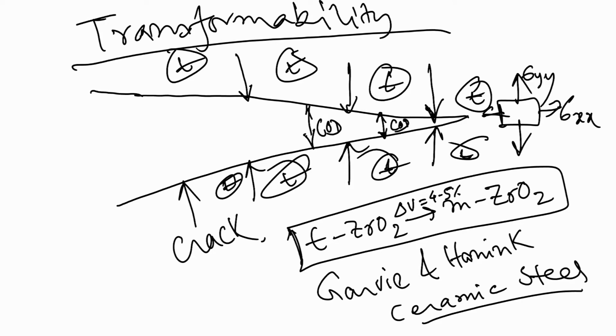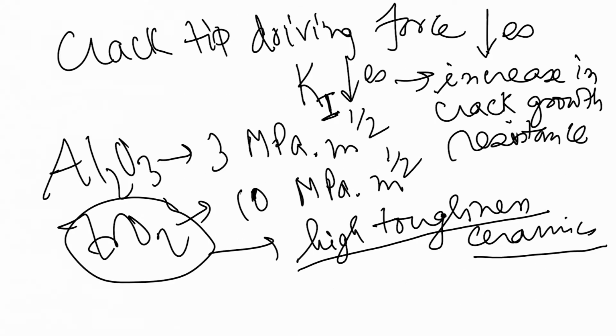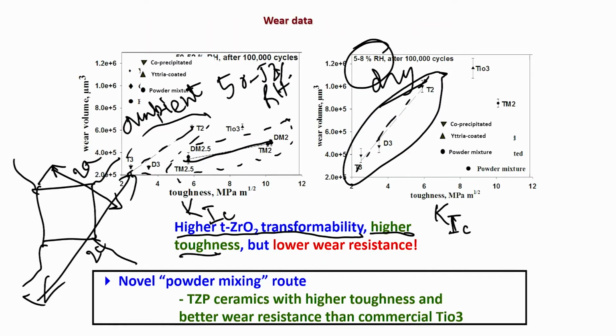The transformability is somewhat similar to hardenability, which is used for steels. If a steel is very hardenable, it means the steel can be hardened very fast by simple heat treatment conditions, without resorting to very aggressive heat treatment conditions. So, higher tetragonal zirconia transformability means higher toughness but lower wear resistance. That is very important, because this lower wear resistance is a concern, and it can particularly limit the applications of these zirconia ceramics